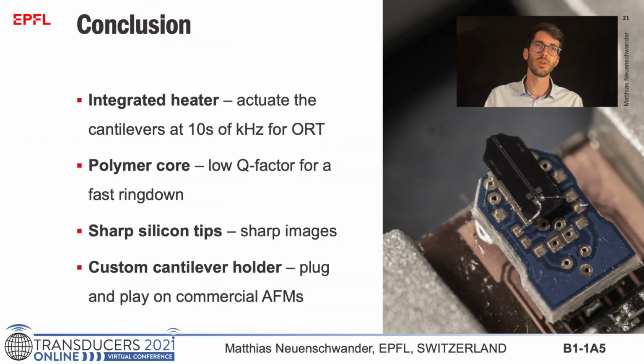To sum up, we present a cantilever with an integrated electrothermal actuator that can push off-resonance tapping rates to tens of kilohertz. The polymer core ensures a low Q factor and fast ring down between cycles. The sharp silicon tip ensures sharp images. With a custom cantilever holder, the probes can be used directly on commercial AFMs.